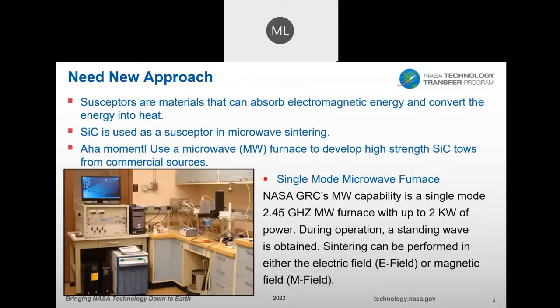So I needed a new approach. And at the time, I was also working on microwave sintering of ceramic materials, and in that case, silicon carbide is used as a susceptor. A susceptor is a material that can absorb electromagnetic energy and convert that energy into heat. So that's when I had my aha moment of using the microwave furnace to try to strengthen the silicon carbide tows from commercial sources. In this case, we have a single mode microwave furnace. It operates at 2.45 gigahertz, and it has a power up to 2 kilowatts. And during operation, since this is a single mode microwave furnace, we are either centering in the electric field or the magnetic field, and this is accomplished by establishing a standing wave within the furnace. Next slide.